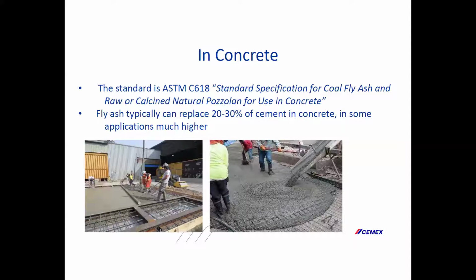So in concrete, there is a standard for fly ash that's used in concrete. It's ASTM C618, which is standard specification for coal fly ash and raw or calcined natural pozzolan for use in concrete. And when it's available and when we can use ash in concrete, typically we use it at 20 to 30% replacement for the cement in the concrete. And in some applications, it might be much higher, as much as 50% or more for certain applications. Next slide.